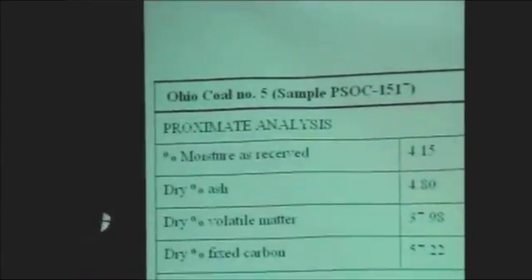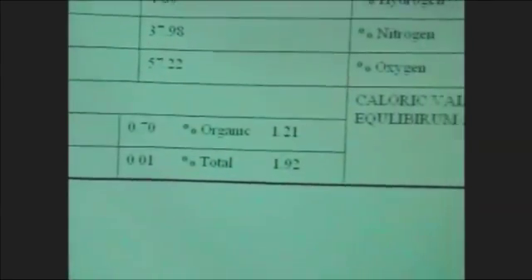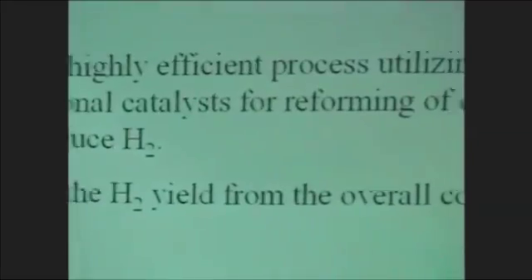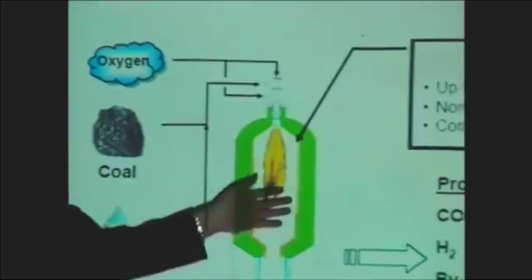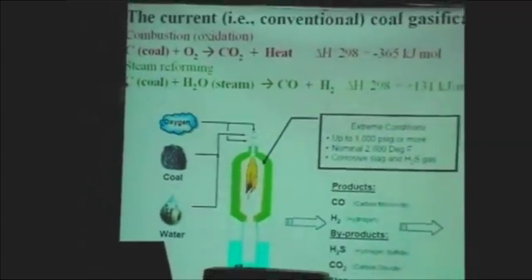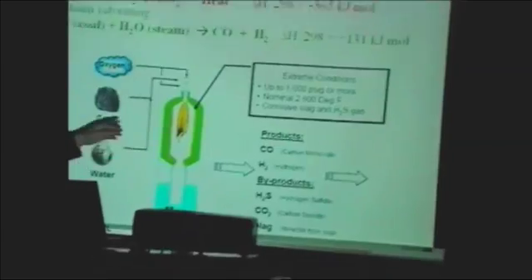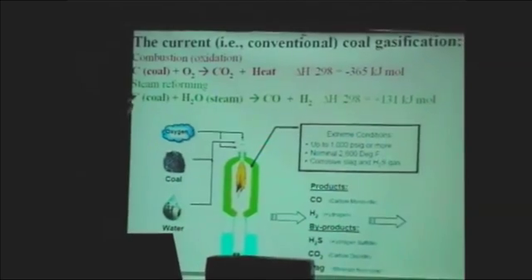In order to do the steam reforming, since we are in Ohio, we have to use Ohio coal to do this reaction study. And so we take the Ohio coal and heat it up to convert it to coke. Because during gasification, if we just take this coal and put it in the reactor, this coal will be heated. All the volatile species will come out. Only coke will stay in the reactor here. So our reforming reaction is really a reaction of char or coke with water. So in order to study the catalytic reforming of coal, we should study the catalytic reforming of coke. So let me share one set of results with you.